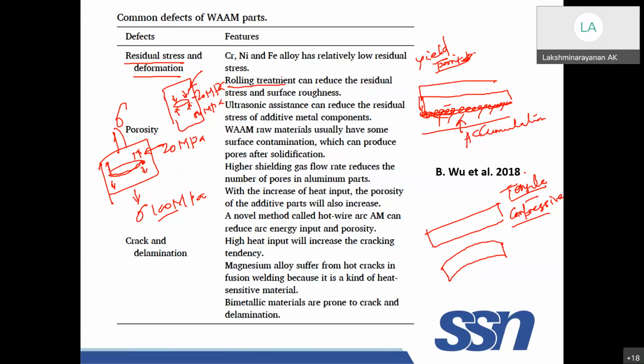To reduce the stress, rolling treatment will be done. Sometimes ultrasonic vibration is also used to avoid this residual stress. One of the other problems is porosity. Sometimes your material will have surface contamination. For example, the wire we are using may have hydrogen atoms because it may be wet, if you do not dry it properly, or it may have some contamination which will cause pores during solidification. So you have to give shielding gas protection and use clean wire. That is another way you can reduce the porosity.